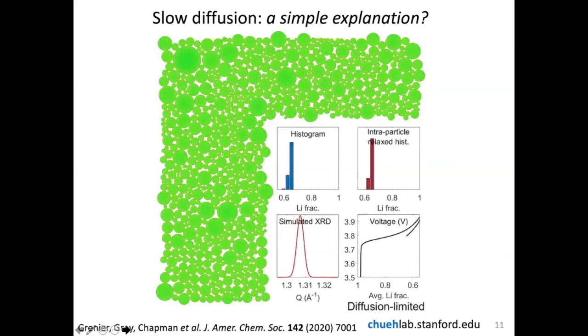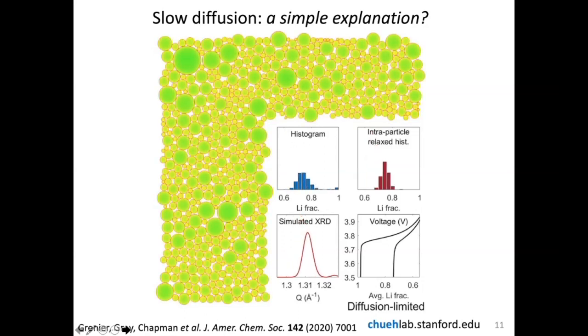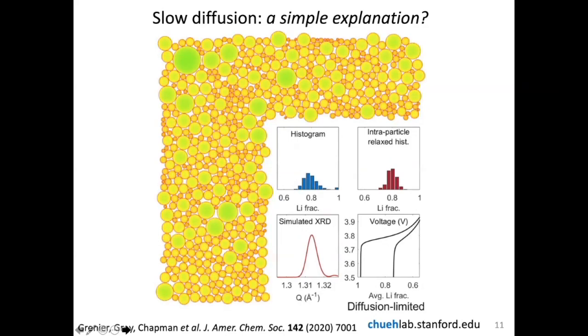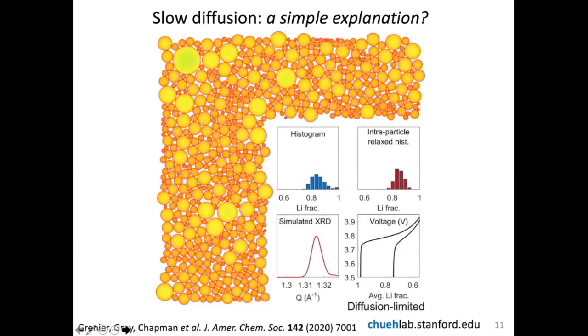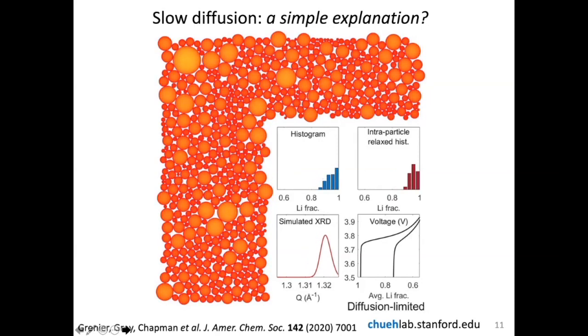When we run a simulation on charge, we don't have this problem. You have the expected solid-solution behavior. It's very uniformly intercalated and deintercalated. So this is the current understanding: slow diffusion within the particle can easily explain why two peaks emerge at a high rate, because you're really competing with the sluggish lithium transport kinetics at the C rate you're operating at. So this seems very plausible, but we want to dig a little bit deeper here and precisely identify the mechanism.